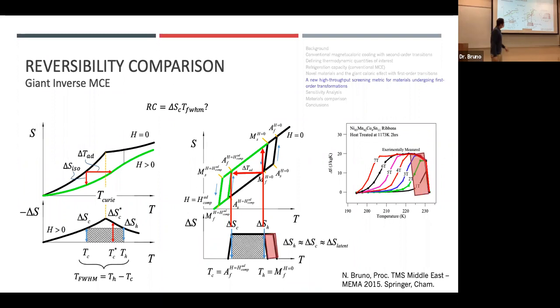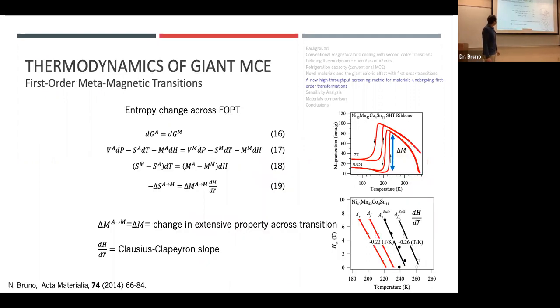All right, so we have a region here that we need to neglect. How do we define the entropy change of a metamagnetic shape memory alloy across a first order structural phase transformation? With ferromagnetic materials, we just use Gibbs free energy, right? But we have two different phases now. We have a martensite phase, we have an austenite phase. And usually we can't just use a single Gibbs free energy. We use equivalents of Gibbs free energy. So the change in austenite Gibbs free energy equals the change in martensite Gibbs free energy.